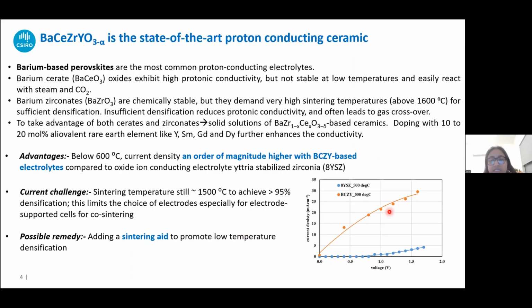So if you see in this plot over here, the VI curve, the current density is almost an order of magnitude higher with BCZY at 500 degrees as opposed to the oxide ion conductor yttria stabilized zirconia.